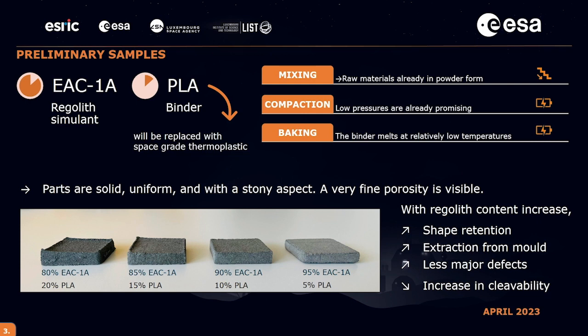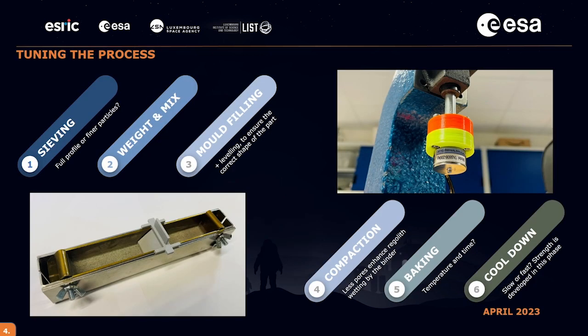So starting from these three steps, mixing, compaction, and baking, we tried to see if we could expand them to better understand the process, to better understand how to control it. So from three steps, we are now discussing six steps. We added sieving, the first one at the beginning, because we didn't know whether it was better to use the full profile of granulometric size distribution or whether it was better to use finer particles or bigger particles, for example. Weigh and mix is trivial, of course. We need to have a uniform distribution of the binder with the regolith to get a solid part.